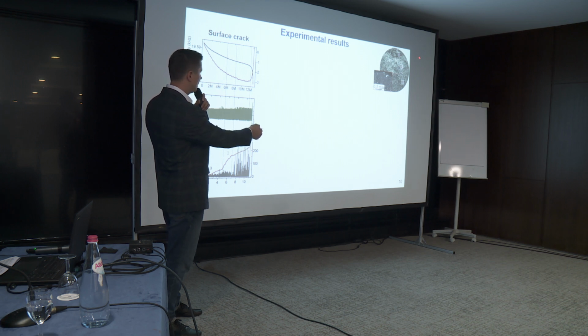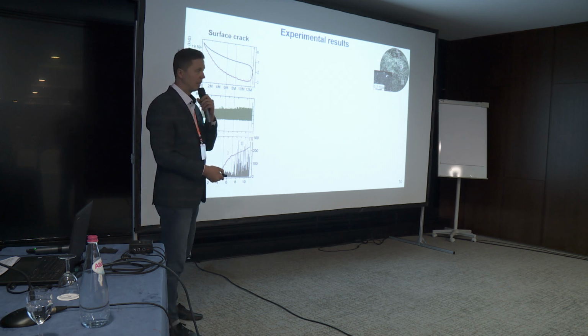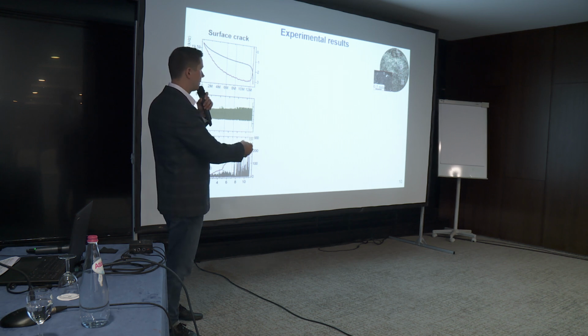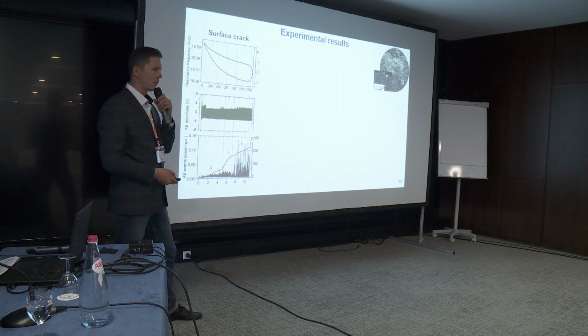This is the optical image, and this was the spot where the crack initiated. You could see clearly with the color, which represents the roughness of the surface, the different modes of fatigue crack propagation. So we have a good correlation here.